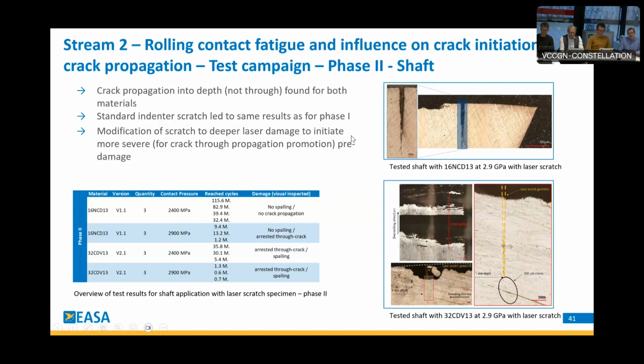You see it here on the right side, on the upper picture: the shaft with the laser-introduced damage, and this is after the test with 2.9 gigapascal. Below you see it here with the 32 CDV. You see the same, the pre-damage and the crack growth, but whatever we did, we didn't achieve a crack through of the part. So for the shaft application, we saw spalling damage. As you see here, the surface is spalling, peeling, but even with this large crack initiation, it does not lead to a crack through of this component.